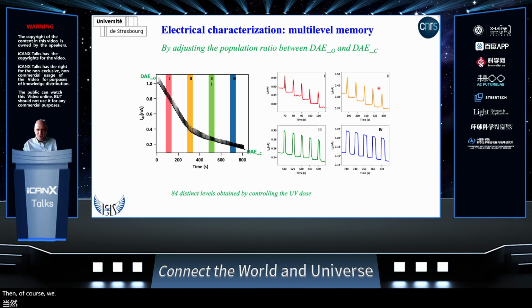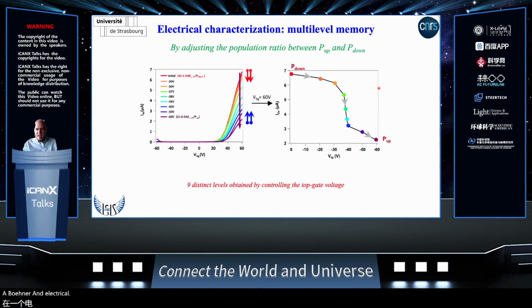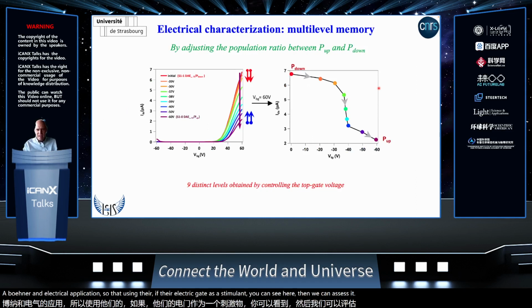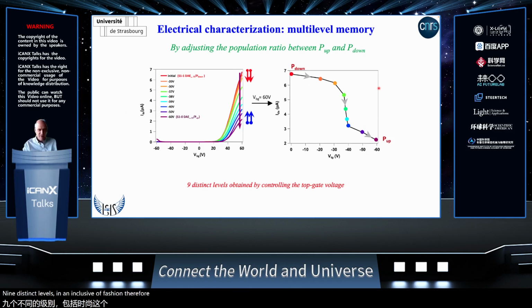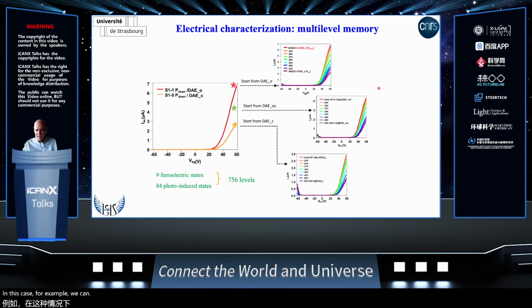Then, of course, we can challenge our approach towards the number of levels we can assess upon electrical application, so using the ferroelectric gate as a stimulus. You can see here that we can assess 9 distinct levels in a reproducible fashion. Therefore, if we combine them, in this case, for example, we can have 756 levels, and in the case we use the very fast laser, we can arrive at up to 11 and sometimes 12-bit memories. So this is pretty much a record, and I want to stress that the two systems are highly stable, and therefore we have a retention time that is hundreds of days.